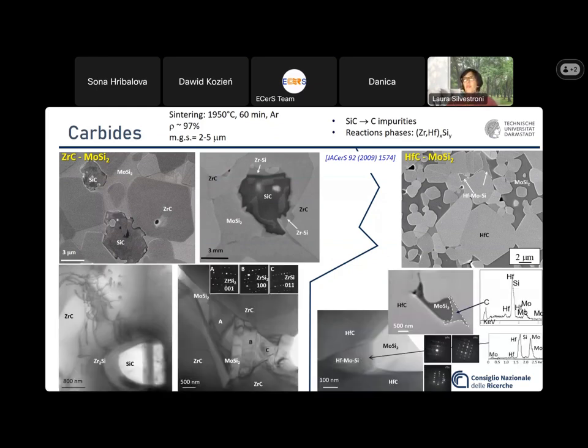And we performed a very thorough microstructural characterization. These were the very first materials, so I was not very skilled yet with the material preparation. So the areas of the thin specimen were quite thin, and I became quite crazy to identify the triple junctions in thicker areas and so on.